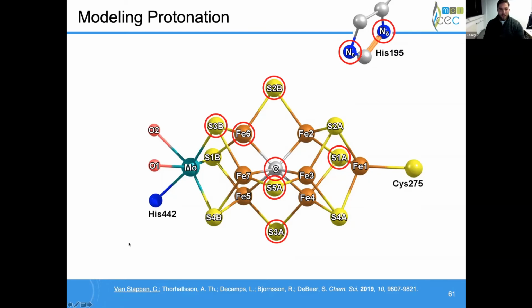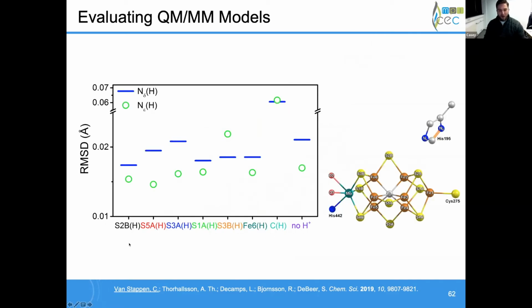And we take all these models and we boil down all of the structural parameters and compare those changes in structural parameters between the calculated E0 and E1 state with those experimentally observed. And we can get this bulk RMSD. Now, I will say that it blankets some kind of harsh violations by a couple of models, particularly when we don't have a proton present on the S3B. There are some distances that change a lot in those that we would have seen in our EXAFS, but nonetheless, our S2B and S5A positions seem to have the best RMSD, and it also seems to favor this N epsilon protonation state of the histidine.